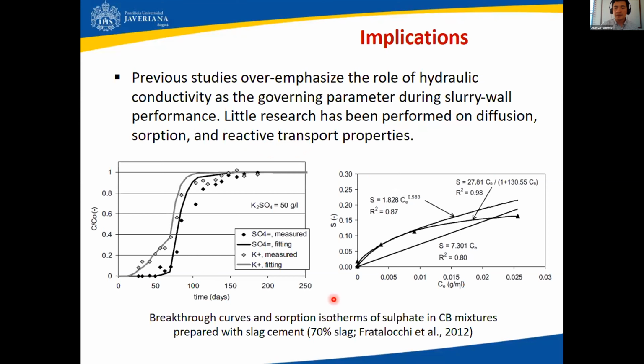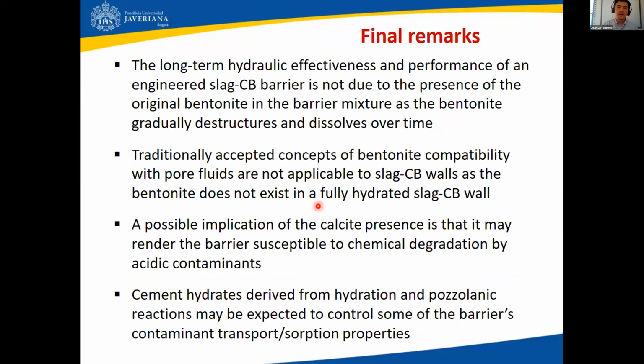And what you're looking at here at the bottom are one of the few studies that we could find, from Fratalocci and others in Italy, on breakthrough curves, sorption properties, and so on, of cement-bentonite mixtures prepared with slag cement. And of course, with this data, you can calculate or estimate diffusion coefficients and sorption parameters as well. So in conclusion, to us, the long-term hydraulic effectiveness and performance of a slag-CB barrier is not due to the presence of the original bentonite. However, the bentonite, of course, is very important for construction purposes, because the bentonite gradually destructures and dissolves over time.